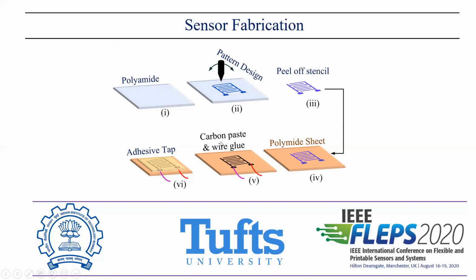Then the carbon paste, which is a conductive paste, was printed on the polymer sheet, and the stencil was completely peeled off. So the pattern of the electrode in carbon paste was on the polymer substrate. In this way we obtain the interdigitated structure of the capacitive sensor on a polymer substrate. Then, in order to bring out the fringing field and to avoid contact or shorting of the electrodes due to water level or soil moisture, we placed an adhesive tape on top of the screen printed electrodes.